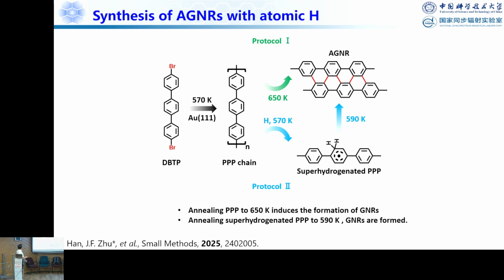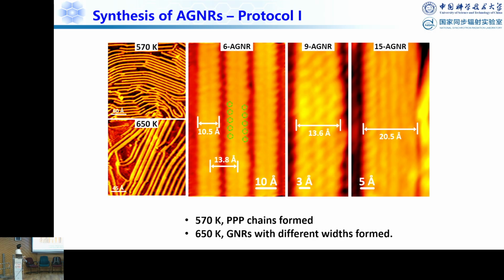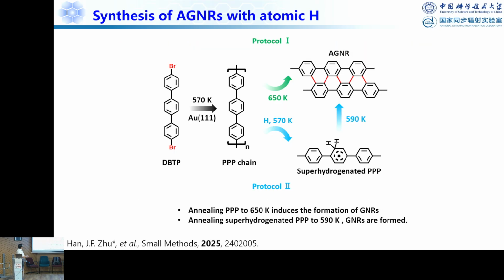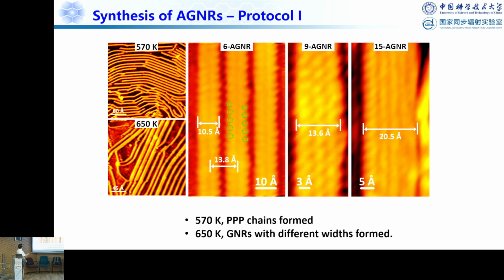The next one we want to show is that we form the graphene nanoribbons with the help of atomic hydrogen. So the atomic hydrogen will really lower the temperature and also increase the selectivity. You can see, we put this precursor, the DBTP molecules, on surfaces. First, they formed the ribbon, which is a PPP chain, and then if we further increase it to 650 Kelvin, now you can see the width getting broader. So if you look carefully, you have these different widths, corresponding to different widths of the graphene nanoribbons.